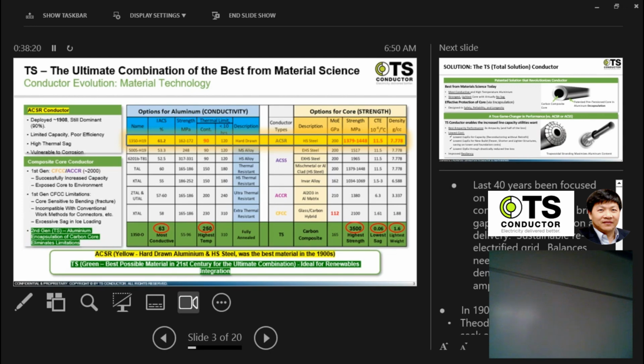The other type of composite core conductor is using glass carbon hybrid core, and I use the generic terminology called CFCC, carbon fiber composite core conductor. This composite core, which is combining glass fiber and carbon together with epoxy matrix typically for that high temperature capability, you do have a high strength out of the core. You do reduce the thermal expansion further, and it's a pretty low density material as well. So in a way, it's actually quite ideal. Now you are able to combine this material with the best possible aluminum for building a conductor. That's the annealed aluminum for pretty decent electrical performance.